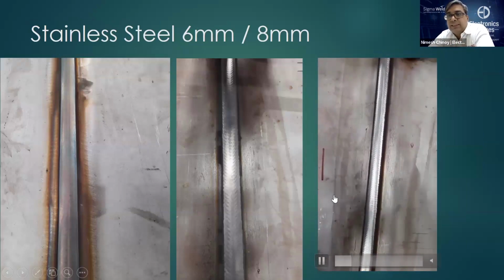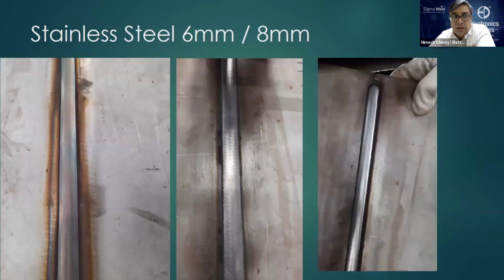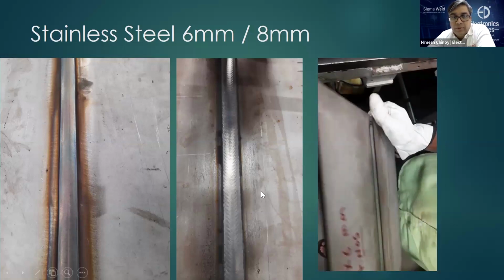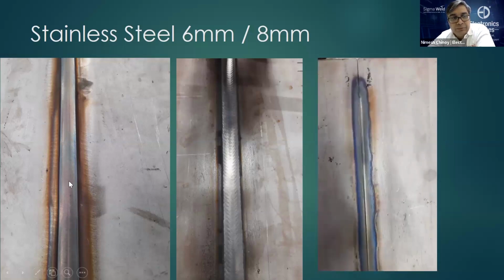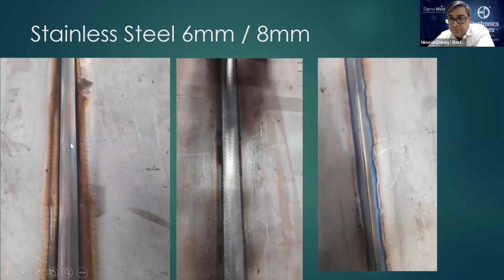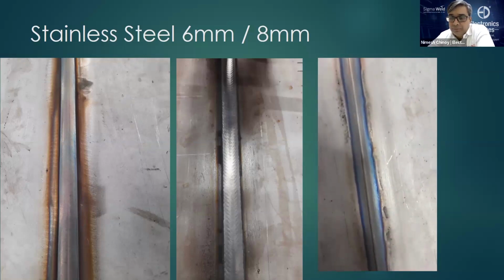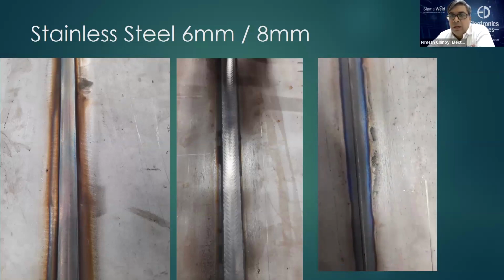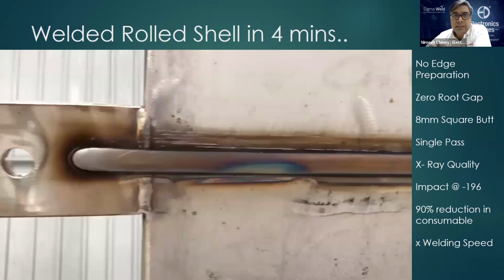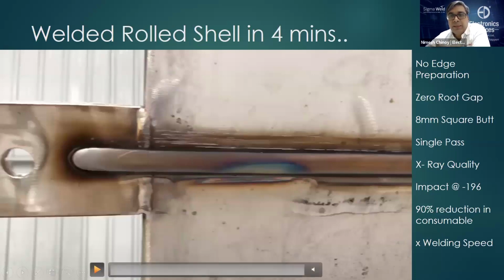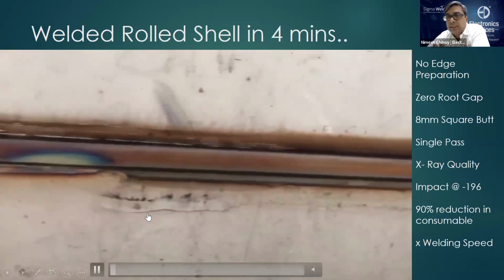So this is a 6 millimeter plate welded on top of it. On the left, you can see the second pass of pulsing done, first pass 100% root joint. You can see the penetration here. And when we talk about efficiency, this rolled shell of about 1.6 meter length was welded in under 4 minutes.